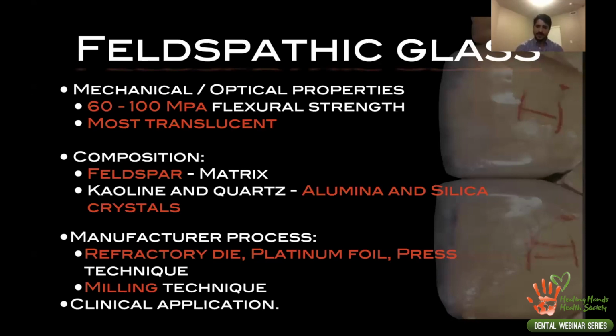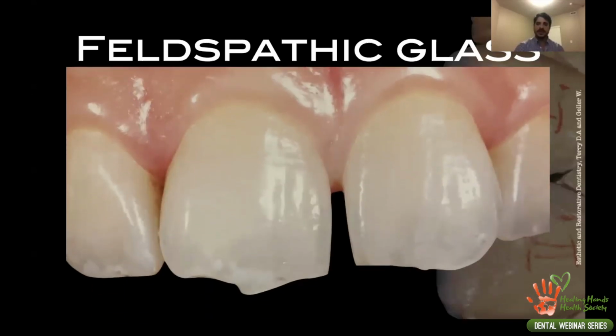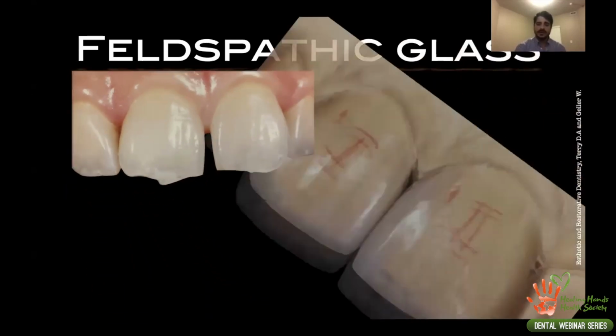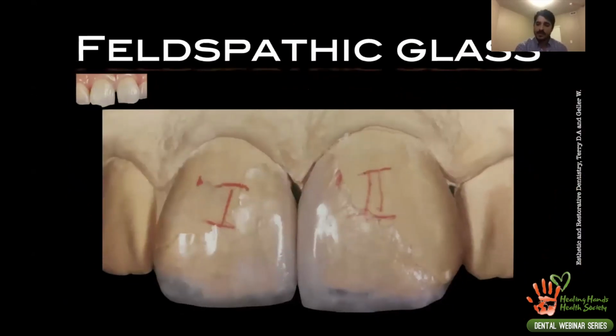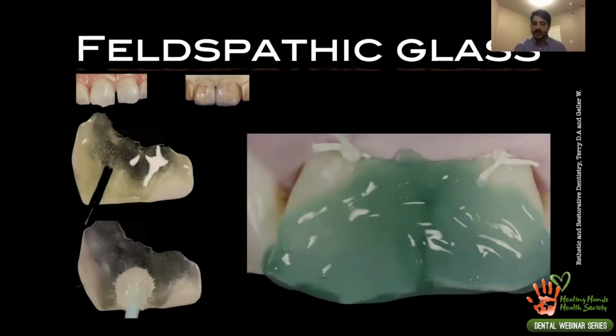But what you appreciate in the following pictures is that it is extremely technique sensitive. You can get to optimal results, but it is extremely technique sensitive. Since you're using a material that is 60 to 100 megapascal, you are relying on the bonding of this porcelain to the tooth. So you have to follow the guidelines to be able to provide a good bonding of the ceramic to the tooth.